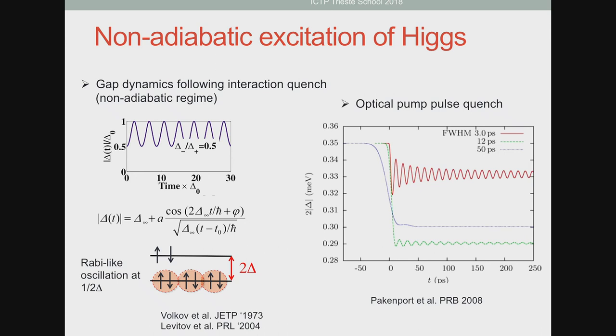So now you can try to compute something that may be a little bit more realistic in terms of condensed matter systems. You can try to compute the response of a BCS superconductor after an optical quench. So you shine a very short pulse on the superconductor, and then you see how it evolves. This was calculated by these people. And what you see is that 2 delta, the superconducting gap, initially decreases. This can be explained by the fact that you are creating particle-hole excitations in a non-adiabatic way. So this is reducing your superconducting amplitude a little bit.